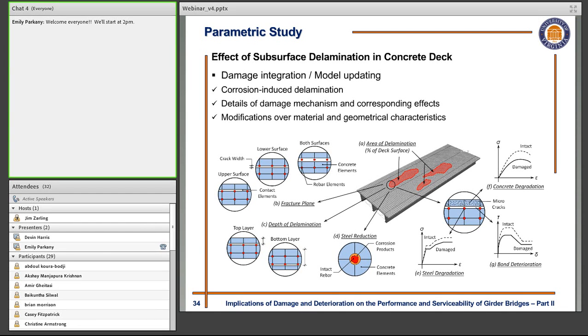As opposed to the previous case, where we included the existence of damage in a fairly simple way by refining the mesh and reducing the thickness, modeling the effect of corrosion in the rebars and consequential effects such as delamination is quite complicated. This is mainly because of the details associated with these damage mechanisms, and sometimes we need very detailed modification over the material and geometrical properties within the damage area. In nature, delamination can occur at any location over the surface of the slab. It is not like the corrosion in the girders that may occur at the mid-span or specifically at the end of the span of the bridge superstructure, and it is usually detected in inspection programs as a percentage of the total area of the deck surface.